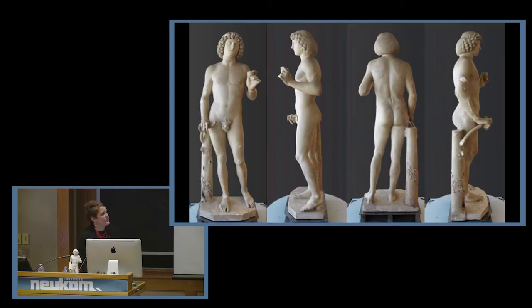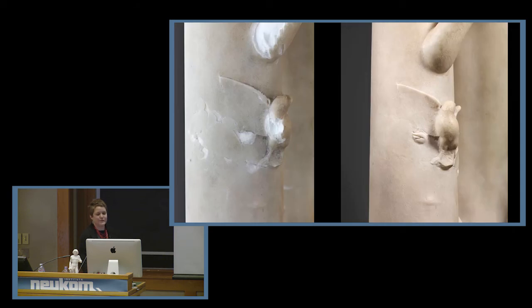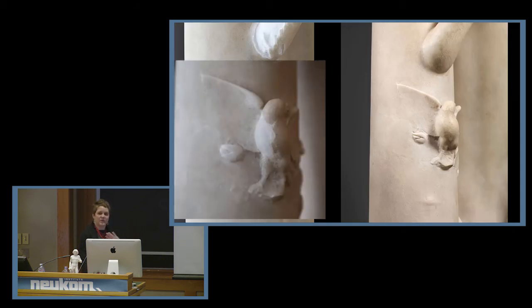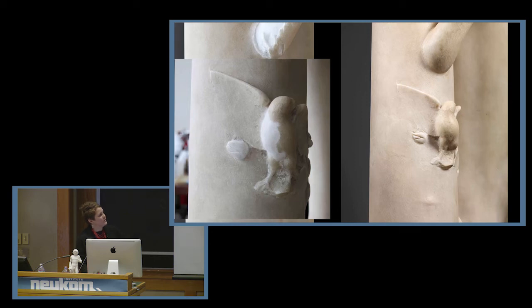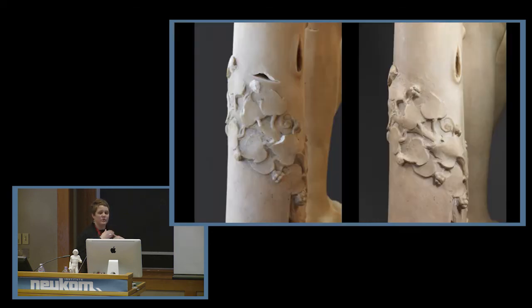And then I just have a few, because we're conservators and we like before and after shots. So I have a few before and after shots just to show you the extent of the damage and the way that we filled it. And we actually used an acrylic adhesive. This is just an interim stage. We used the same acrylic adhesive, but we mixed in inert materials to create something that looked similar to marble, and then it was toned with a PVA resin mixed with dry pigments.